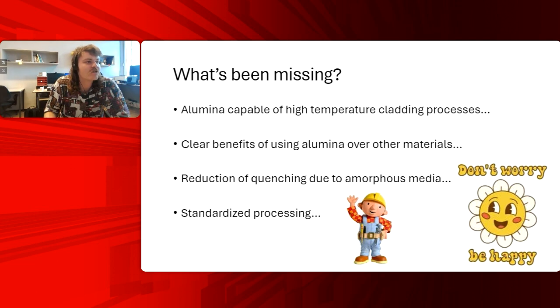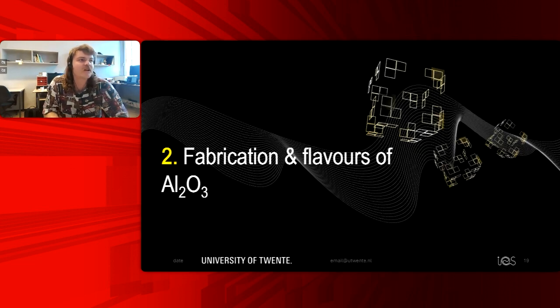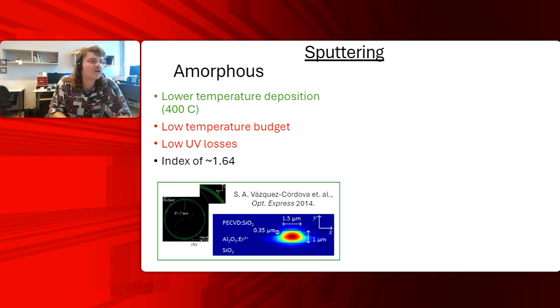So here's some fabrication flavors that we do aluminum oxide with. In the past, a lot of work has been done on amorphous aluminum oxide, some more glassy material, which has a lower deposition temperature. However, this lower deposition temperature lends itself to an amorphous material, which has a smaller thermal budget, therefore can't be used with LPCVD silicon oxide, where you see PECVD in the bottom left image here, does not have low UV losses and has an index of about 1.64.